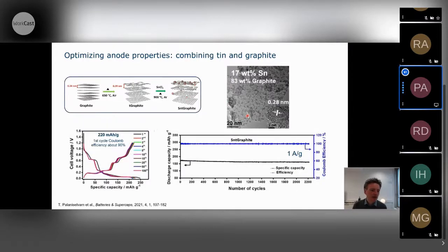And these are the electrochemical results. You can see here a voltage profile which very much looks like tin. So most of the capacity comes from tin, and additional capacity comes from the graphite. And the graphite part is extremely fast. Okay, the tin part is a bit slower, but the graphite part is faster. At a rate of C/10, you get 220 milliamp hours per gram. The Coulomb efficiency in the first cycle is around 90%, which is very good.